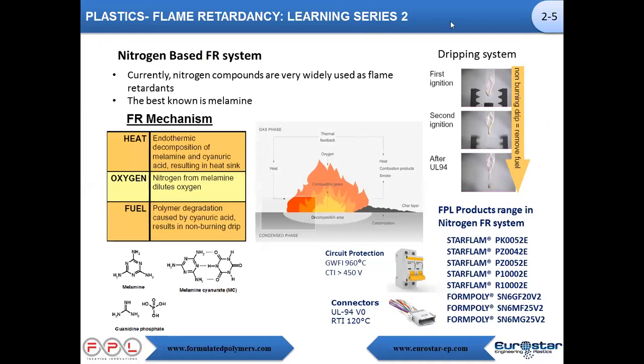It decomposes the melamine, which then creates droplets. And these droplets are very small and carry the polymer away from the fire and the heat of the sample. This explains why it works very well for very thin material, down to a very low thickness. We have V0 listed down to 0.4 millimeter.